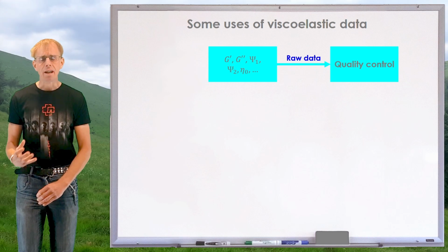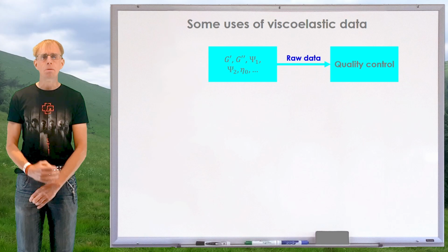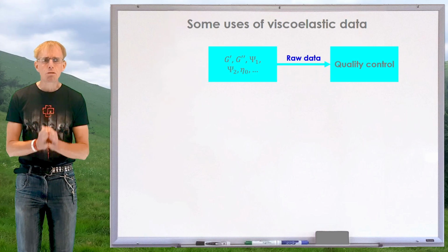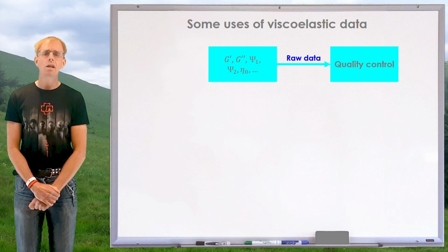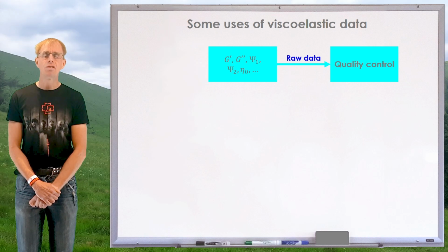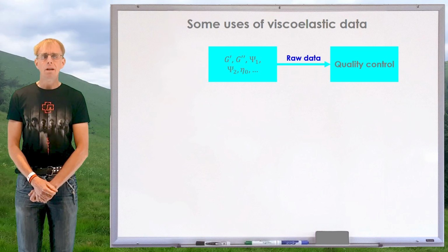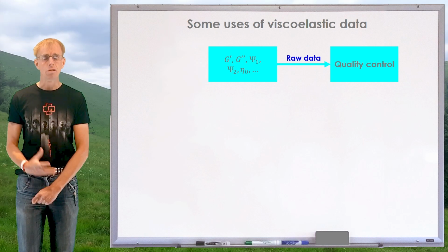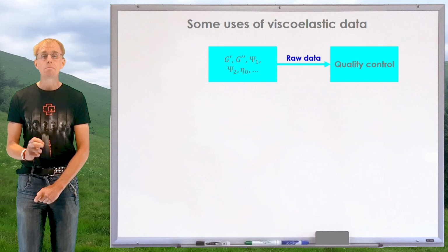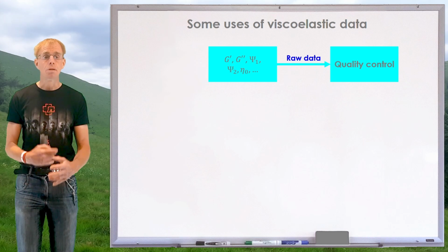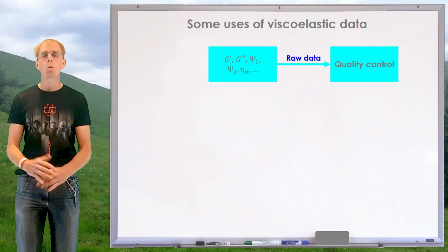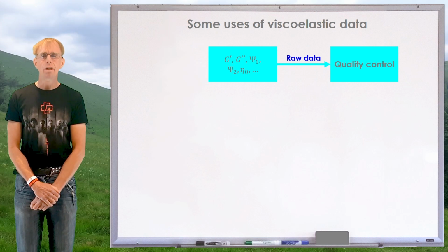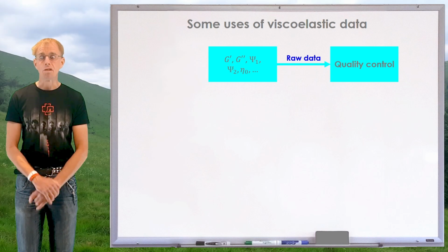We've seen in the last lesson that simple metrics such as the melt flow index only give us a very, very small bit of insight into the full nature of the viscoelastic response of a polymer. So it's perfectly plausible to have a number of different polymers with slightly different architectures with the same melt flow index that won't end up processing in the same way. And so we need more data to actually do that batch to batch quality control to ensure that we've got a stable process.